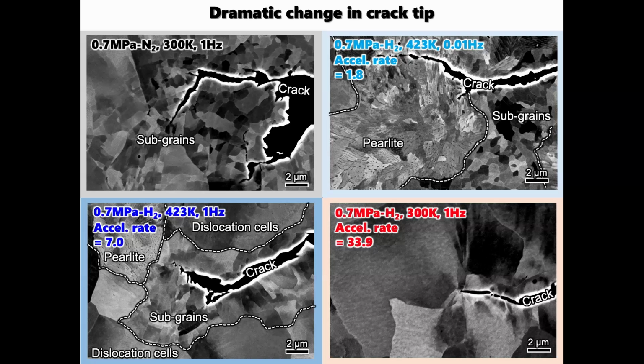When increasing the loading frequency to 1 Hertz, the region with subgrains became shrunk just around the crack wake. And you can see the dislocation cell structures surrounding the subgrain regions. Also, when decreasing the temperature to room temperature, which causes the maximum acceleration, no such developed substructures are generated. So fatigue crack propagated without any intense and extensive plasticity during fatigue process.